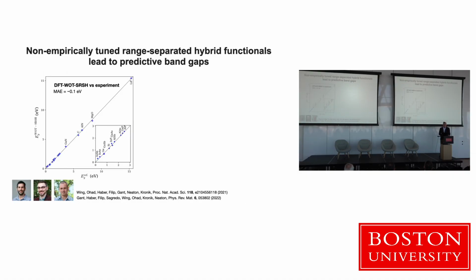And so what we've been able to show in recent years with some collaborators at the Weizmann Institute is that we can develop a non-empirically tuned hybrid functional that predicts very high-quality band gaps for a wide range of semiconductors. So this is a plot on the left of gaps generated with this method versus experiment. And the MAE is really impressive. This is about 25 materials, and the data set now is like 40 or something. The real limitation is the reference data. It's not easy to measure this gap. This is a very hard measurement. You have to remove the phonons, you have to remove excitons, and so that's a little bit of a limitation, but it looks pretty good.